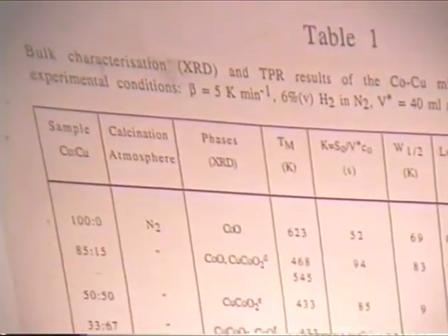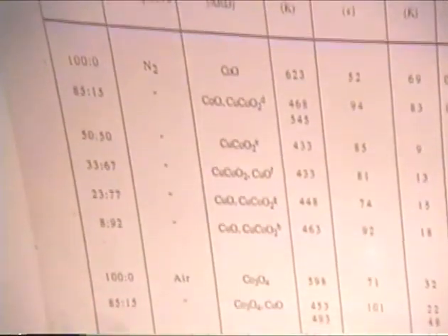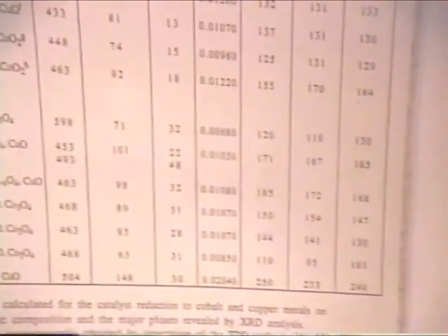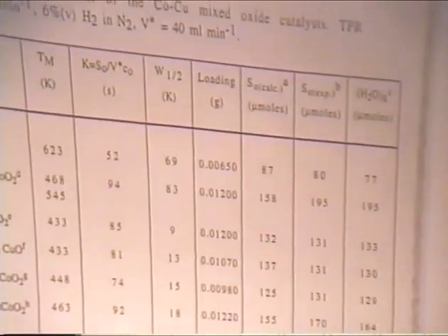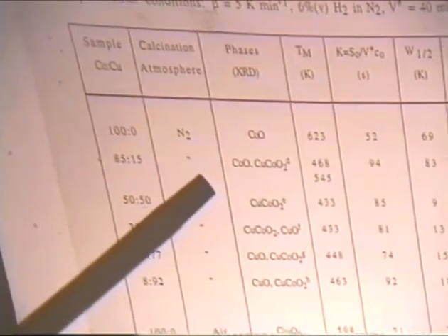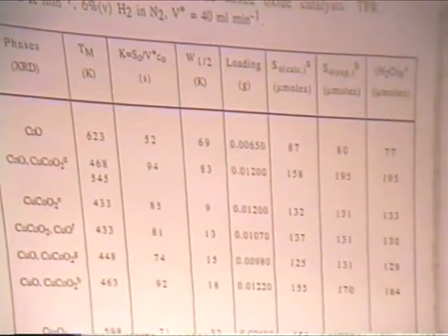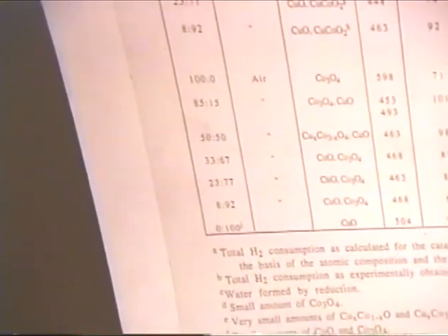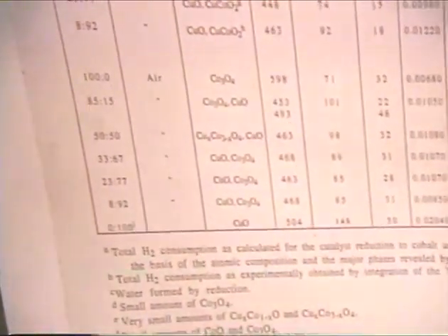So, in this table, the phase characterizations by X-ray diffraction analysis are reported together with the TPR results, which will be discussed later on. If we look at the nitrogen calcined catalysts, we can see that the pure spherocobaltite formed under an inert atmosphere the cobalt 2+ oxide, CoO, which is expected to be the stable phase of cobalt oxide under an inert atmosphere. The first addition of copper formed, beside the cobalt 2+ oxide, the CuCoO2 phase, which, as the XPS results will prove, was formed by copper 1+ and cobalt 3+ species.